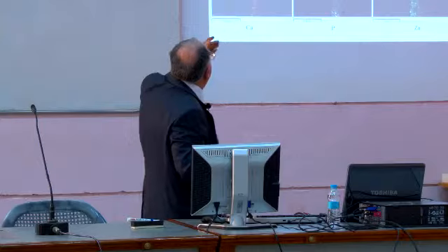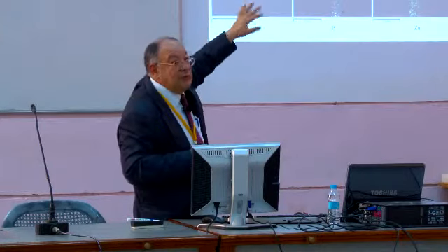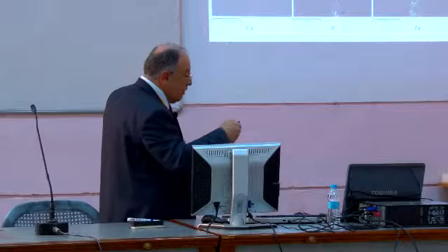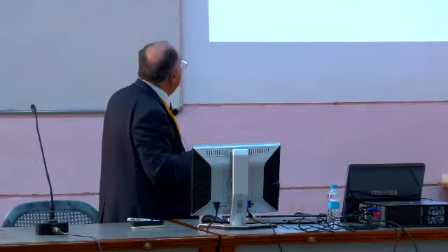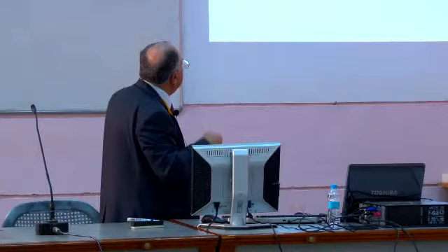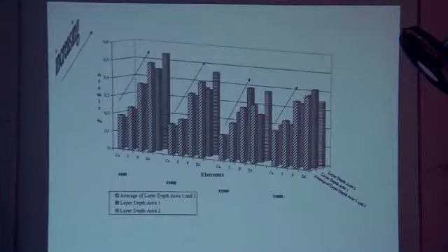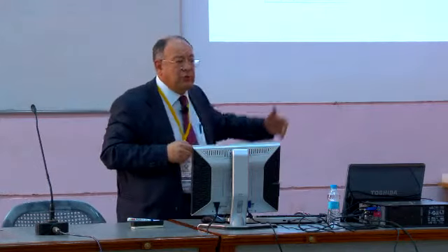I'll show you only the 4,000x, because we also did 5,000x and 1,000x, and it would take too long. But here is the non-wear area, and I put here the AFM and X-ray results. We did cartography for calcium, phosphorus, and zinc. It's very colorful and really protects the surface. Is it true? Yes, because on X-ray you see calcium, phosphorus, and sulfur detected on this part, but here there is nothing. And we did some statistical results.